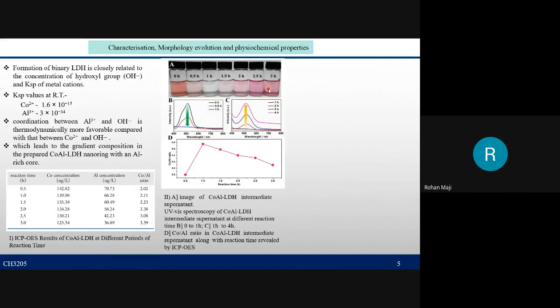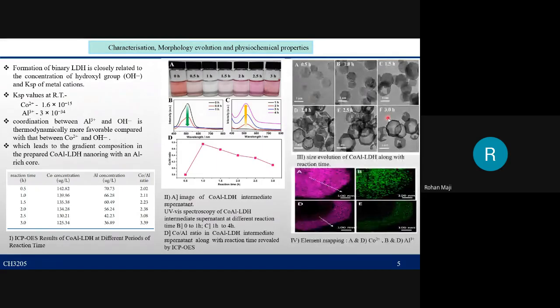And the TEM images confirm that the LDH maintains the integrated regular hexagonal nanosheet structure. And with time, the nanopore appears in the middle, but these are irregular in shape. And the outer diameter continues to grow, but this maintains the regular hexagonal shape.